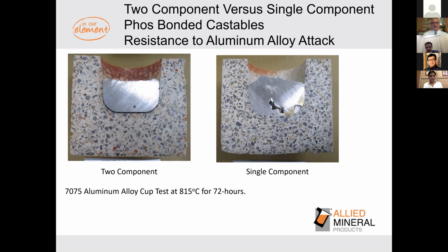So that's why we run the test at this high temperature. We would hope that you would not run your metal temperature that high, but to have a very rugged test, we run at this temperature. And you can see using water with a dry component of Phos, we were able to maintain the refractory's ability to totally resist aluminum reaction and reducing of the silica in this refractory.